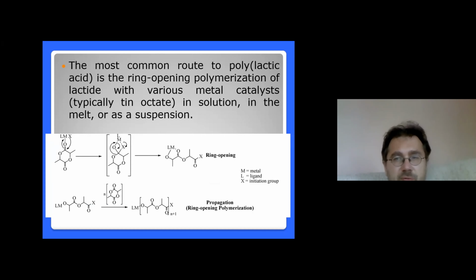So the most common route to production of polylactic acid is the ring opening polymerization of lactide with various metal catalysts, like tin octoate, in solution, in melt, or in suspension. So as I said, we know many methods of production, but there is some problem with this tin catalyzation process. But what I'm showing you is the typical way, but we know different catalysts now.